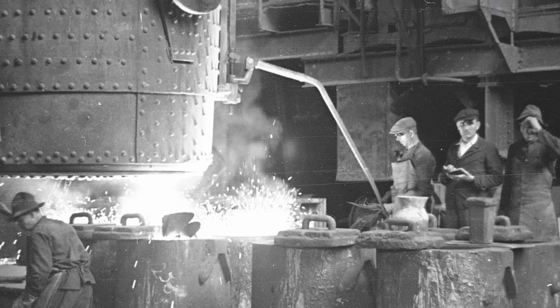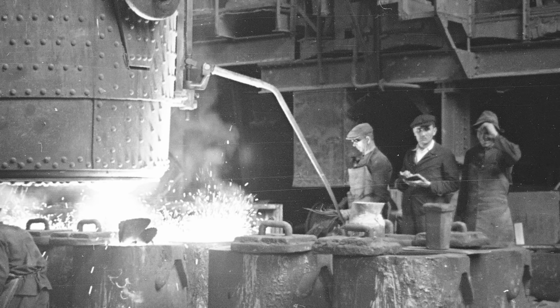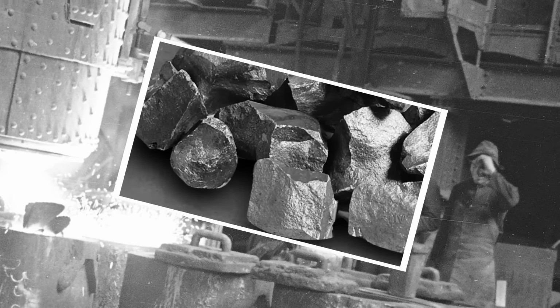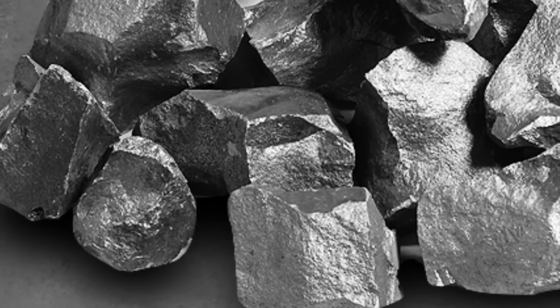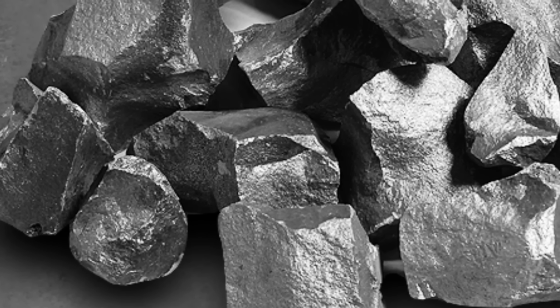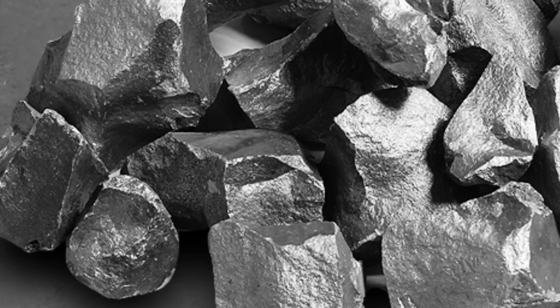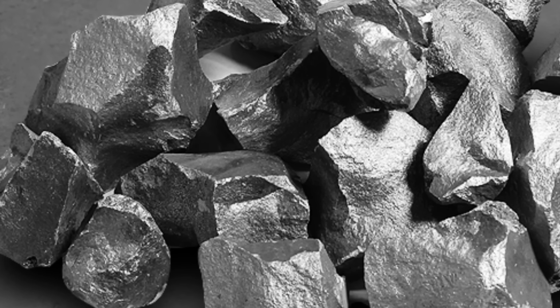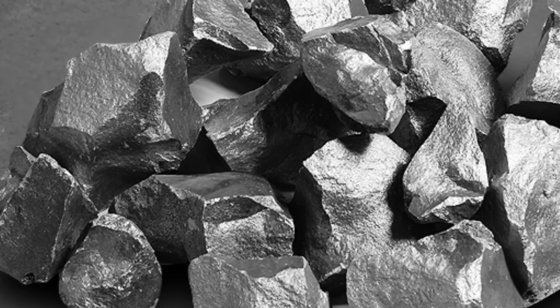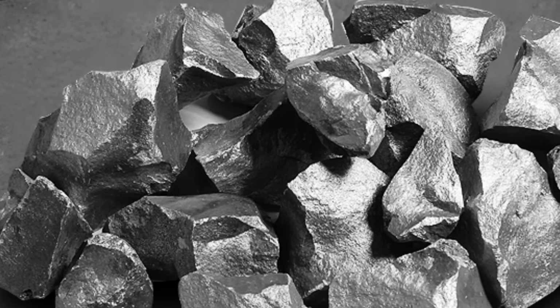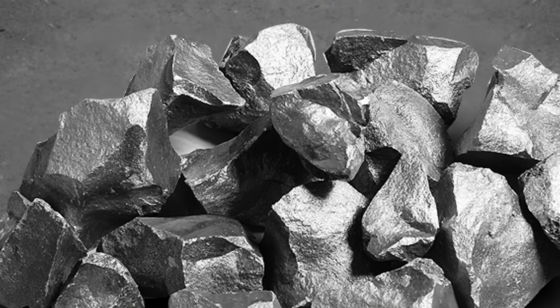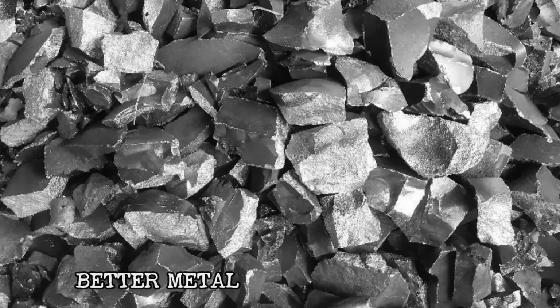A metallurgist named Robert Mushet solved this by developing Spiegeleisen, a carbon and manganese alloy that workers stirred back into the converter in carefully measured amounts. Too little, and the steel stayed soft. Too much, and it turned brittle enough to shatter under load. The exact failure that had started this entire chase for better metal in the first place.